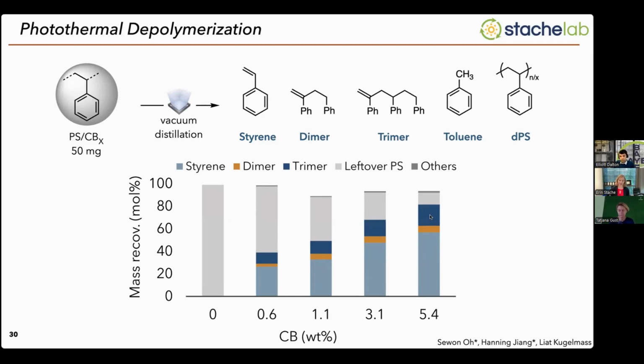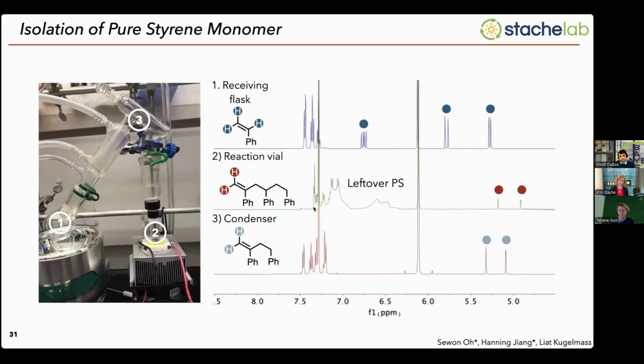So we're very excited that we could take carbon black, use it as a photothermal agent to depolymerize these lab synthesized polystyrene composites. This is our reaction setup. You can see here, we're irradiating the vial. It goes through a distillation setup so that we can recover pure styrene monomer in the receiving flask. You can see up here in this proton NMR, this is pure styrene monomer. All those peaks belong to styrene. In the reaction vial, we have leftover polystyrene with a little bit of trimer. And then in the condenser, we have the dimer. These are just separated based on boiling point.